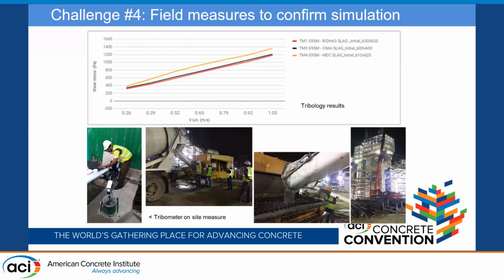Through the tribometer testing, without doing any mock-ups or putting any concrete in the pipe, we determined that the low shear yield stress we got when we used the slag coming in from China was the best solution for this project. It helped the project make the decision to purchase super sacks of this material from China, where a local manufacturer reprocessed or rebagged it or put it into tankers so they could get it into our silos. They paid that extra. They needed that material to make this project work, and we were able to confirm that with the tribometer testing.